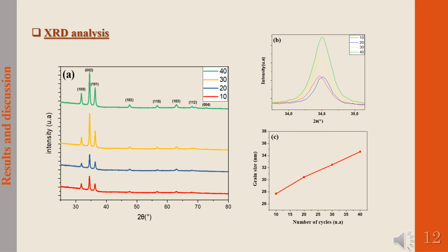From the X-ray diffraction analysis, we observe that the films produced are pure and well crystallized in the hexagonal phase. The nano-sized crystallites tend to agglomerate into larger grains following the film post-thermal annealing, which is in good agreement with the evolution of grain size of zinc oxide reported by scanning electron microscopy.